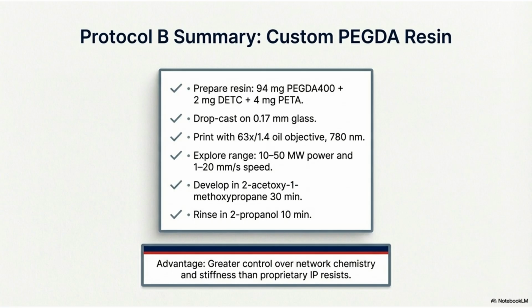Protocol B, for custom PEGDA resin, requires preparing the specific resin mixture, drop casting on glass, and printing with an oil objective. Explore a power range of 10 to 50 milliwatts and a speed of 1 to 20 millimeters per second. Develop in 2-acetoxy-1-methoxypropane, rinse in 2-propanol. This protocol offers greater control over network chemistry.